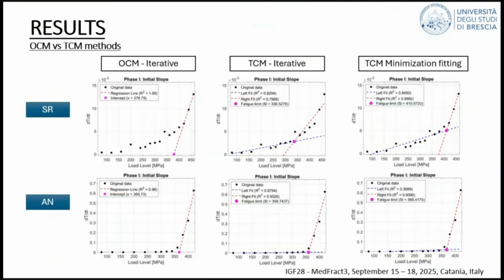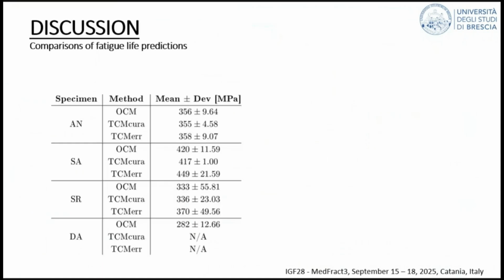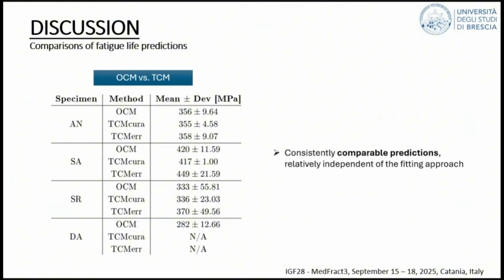So the second type of comparison was among the fitting methods. Here we can see an example for the stress relief against the annealing condition. What we can see, especially if we compare the numbers, is that if we take an average value, considering for each fitting strategy the mean result of all the thermal indexes that we have investigated, is again that there is no clear difference between the various fitting strategies. At least in this case study, this was not a really significant parameter.